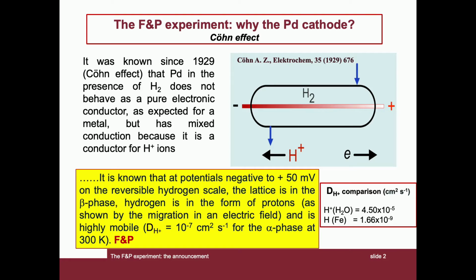This state is unique in cases of a metal-hydrogen interaction. For comparison, the diffusion coefficients of the proton at 25 degrees C in liquid water and that of the hydrogen atom in iron in the solid state are reported. The difference in order of magnitude illustrates the peculiarity of the hydrogen-palladium system.